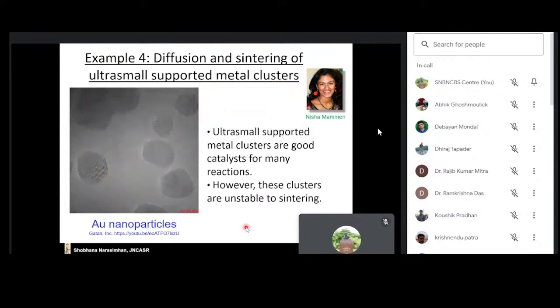So I'll show it to you here. This is an electron micrograph. You already saw these two nanoparticles coalesce and form a larger nanoparticle. And if you watch this video for a little while longer, you will see that these two nanoparticles also will diffuse and coalesce. And so ultra small supported metal clusters, though they are good catalysts for many reactions, are unstable to sintering. So we would like to understand how this process of sintering occurs. Are all metals equally likely to sinter? And also, what is the process by which sintering occurs?